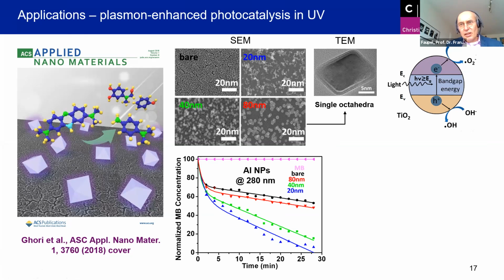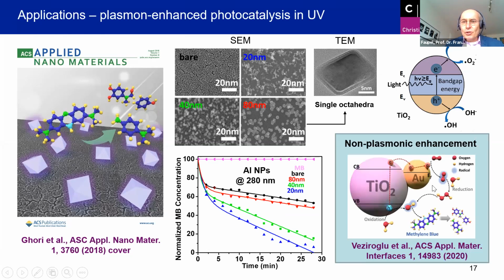In our recent activities on photocatalysis, we do not only use plasmon-enhanced photocatalysis, we also use metallic nanoparticles, which in principle also exhibit plasmonic properties. But here we take advantage of simply charge transfer, which is also very effective in enhancing the photocatalytic activity. So you prevent recombination by trapping the electrons at nanoparticles. More details are given in this recent publication.